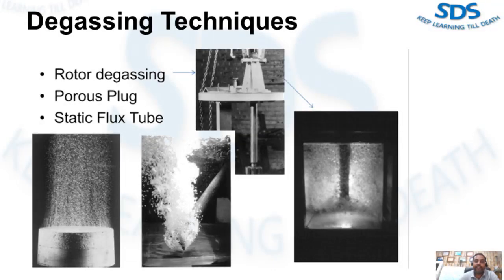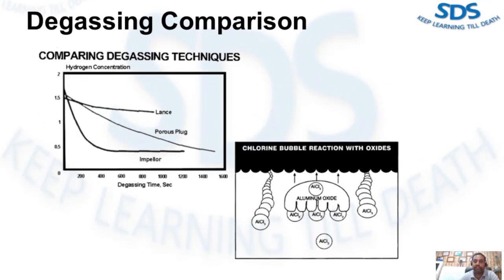Okay, if we talk about the degassing benefits, degassing has a beneficial effect on melt cleanness. Gas fluxing removes hydrogen, and also floats Al2O3 inclusions. When chlorine is added to the inert gas, there is an enhancement of inclusion removal. The chlorine lowers the surface tension between a solid oxide particle and the aluminum melt, facilitating the ability of the gas bubble to grab the inclusion. Okay, if we compare all these techniques, all three techniques, lance, porous plug, and impeller, furthermore, since oxide particles themselves can hold on to hydrogen atoms, any cleaning technique that assists in removing inclusions can also lower the hydrogen gas content with a resultant decrease in porosity.